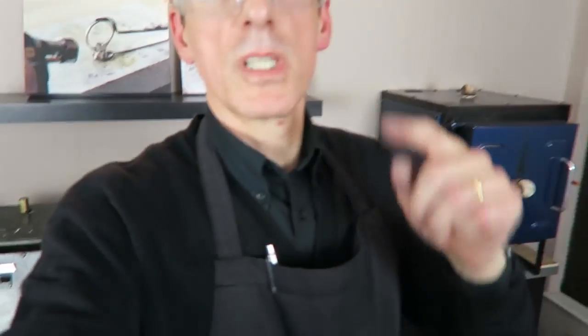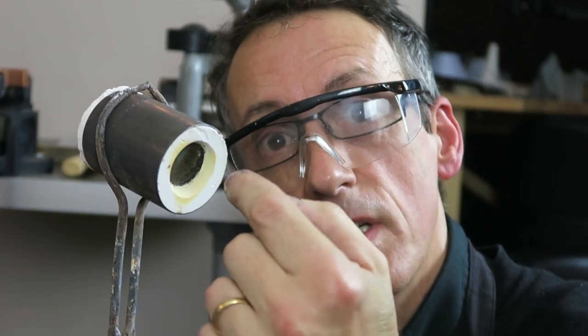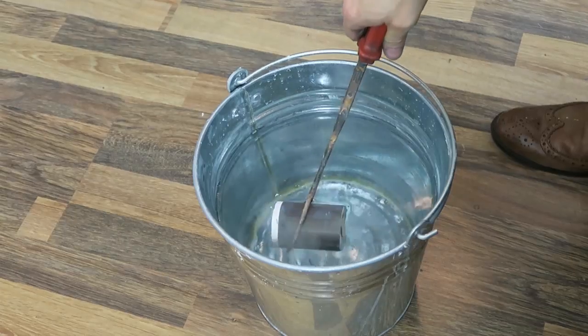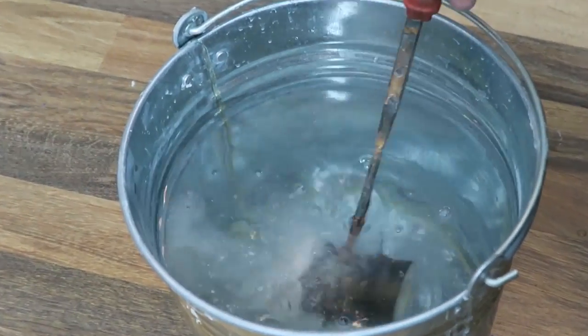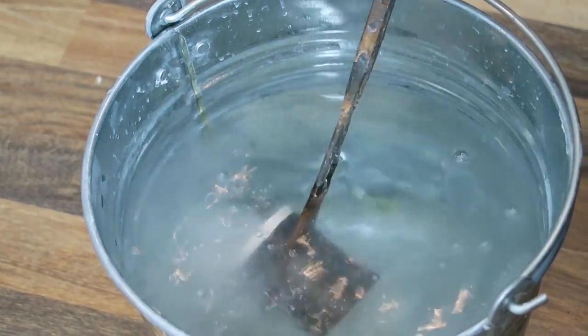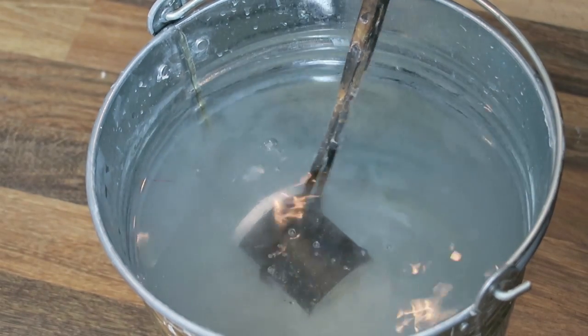Whilst that one is spinning around, as you can see, I'm going to put the silver one, which should have cooled down enough now, and I'm going to plunge it into this bucket that we've got down here. And what happens now is the shock of putting this flask in the cold water will make like an eruption, and it will release the silver pattern that we've got inside this investment. Although I can't show you what's in this one, it's a secret. Not a very good eruption, this one, because the silver has cooled down quite a bit. The gold one is going to be a lot more spectacular.